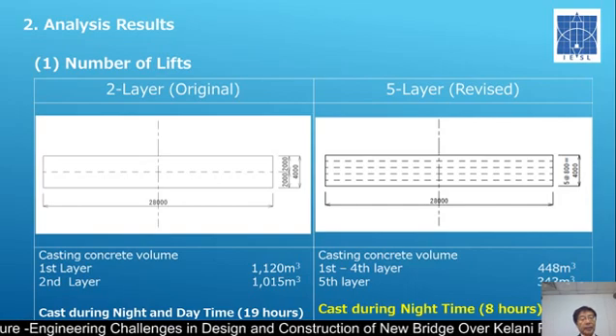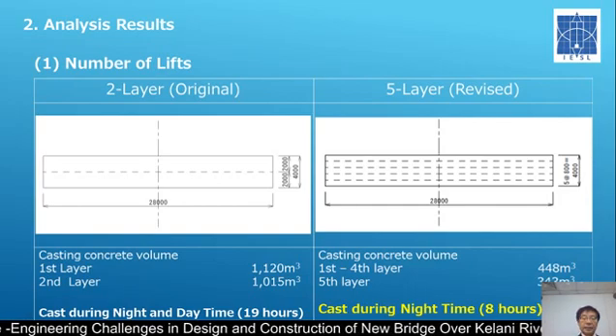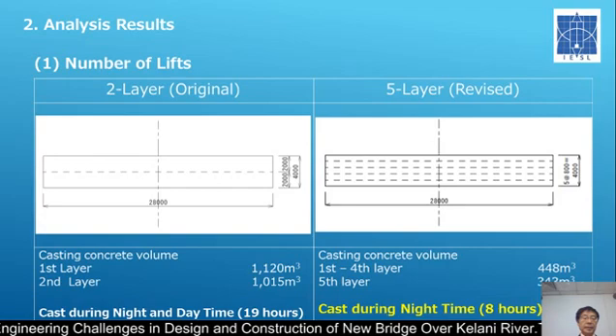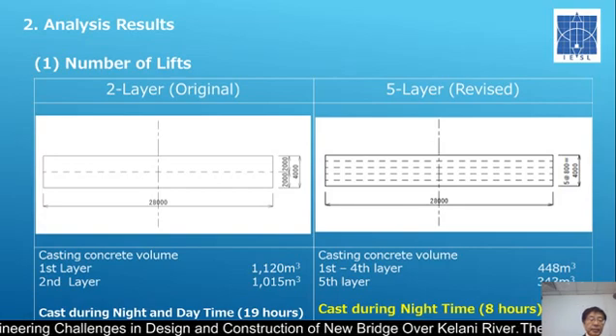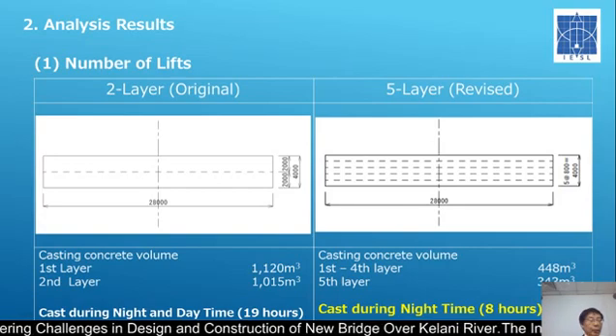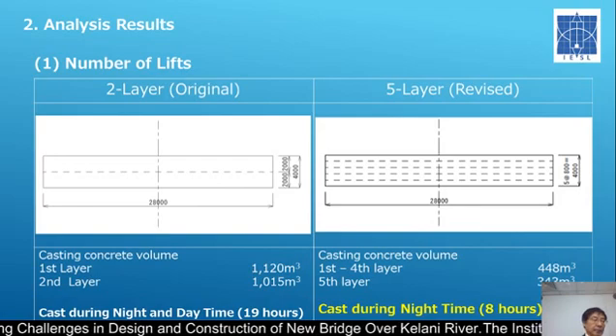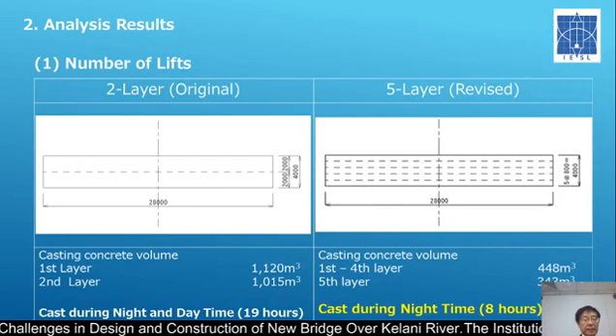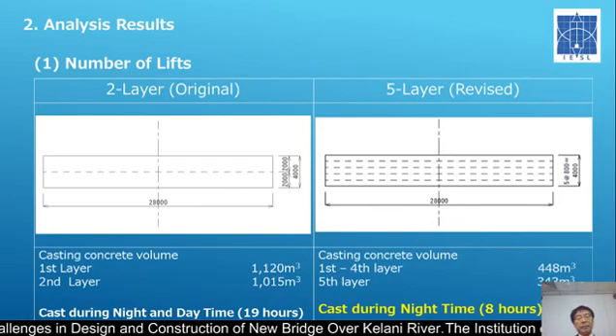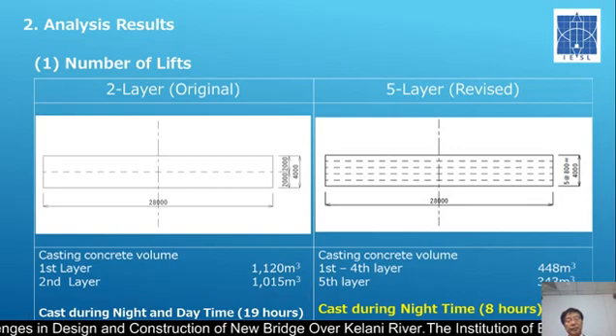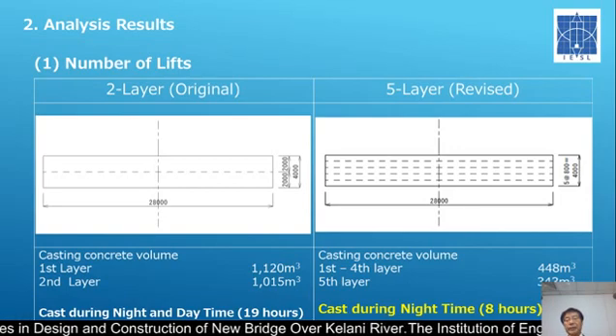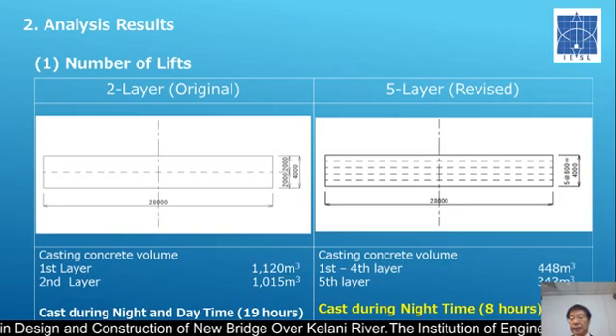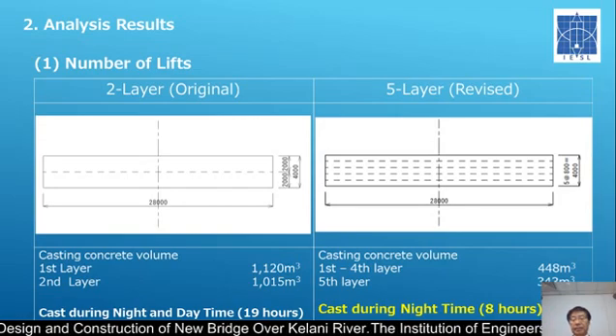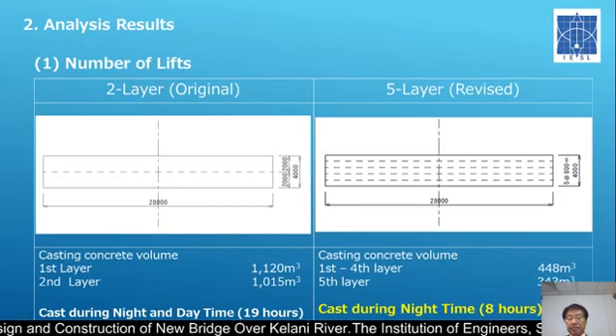One is casting 2 layers. The other one is 5 layers. 2 layers means casting the concrete about 1,000 cubic meters per layer, and the casting depth is 2 meters. Whereas the right hand side is 5 layers, which is 0.8 meters each, but with 5 layers.